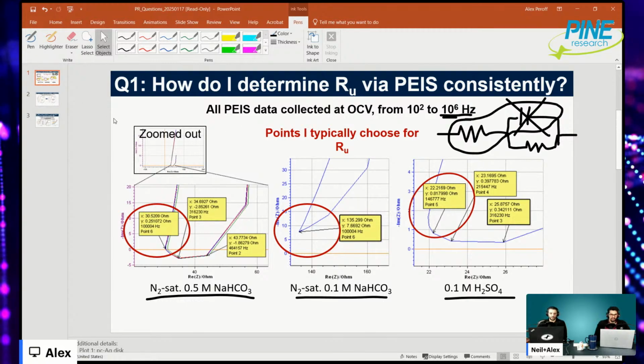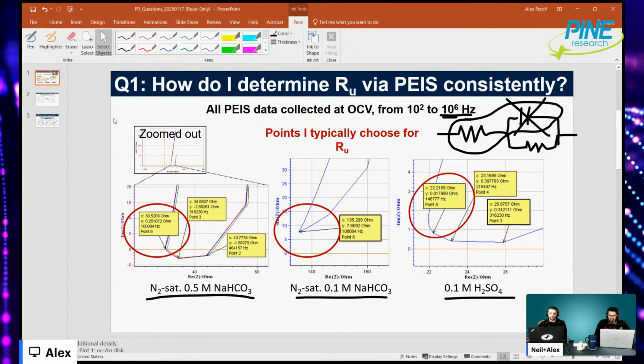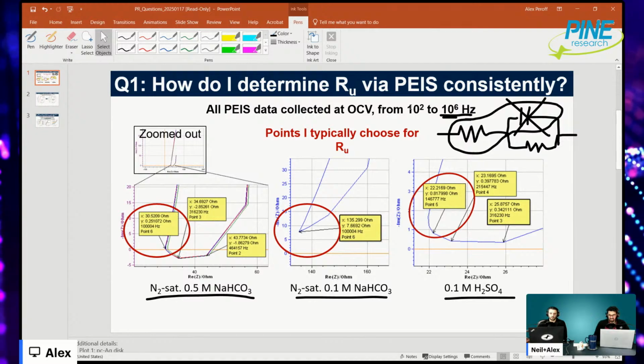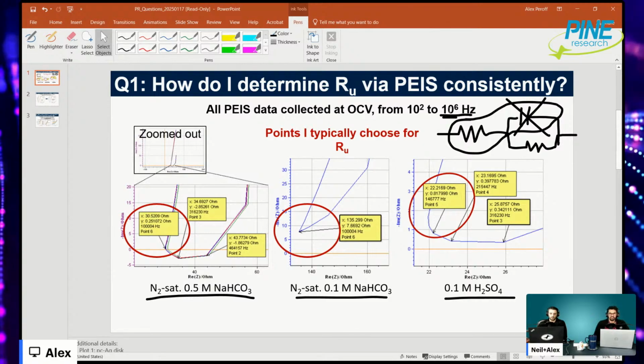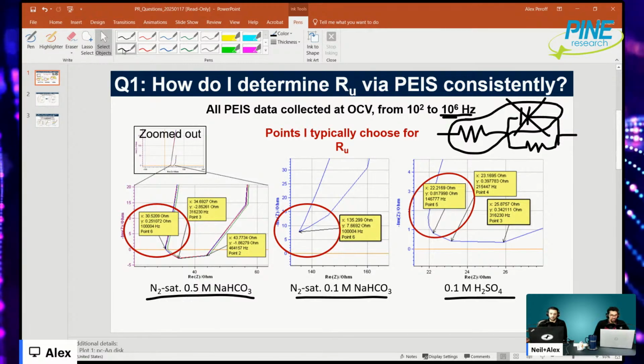So my view, my approach, or opinion is that you don't need to go from 10 to the 6 to 10 to the 2. You can just stick within a much higher frequency region. You can go from 10 to the 6 to say 10 to the 4, because you're not going to need these data points when collecting the solution resistance values. But my viewpoint, at least, is you want to pick values where.